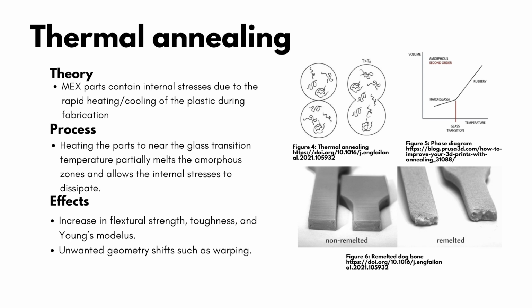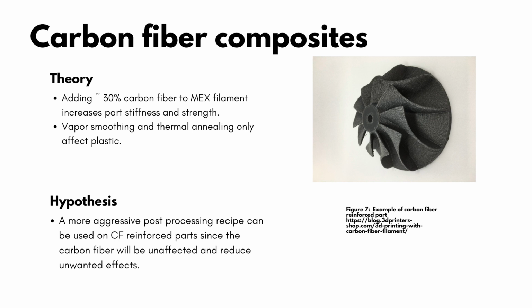Now the bottom figure on the right shows an extreme best case scenario where a part is annealed so well it no longer breaks on just the layer lines during a dog bone tension test, showing a clear strength gain. Moving on to the use of carbon fiber composites.